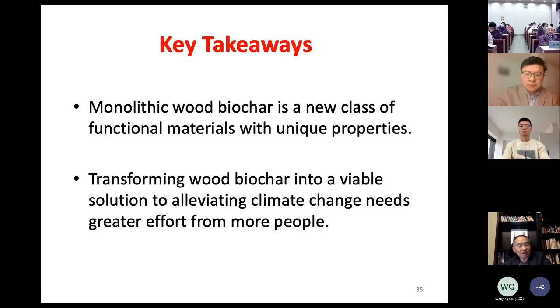So to answer your question, both have to be considered, in terms of the specific surface area and the porosity. We can have extremely highly porous carbons, like aerogel, extremely porous, with porosity over 90%. But because it is very light, the SSA is actually very low. So there is a trade-off between them.